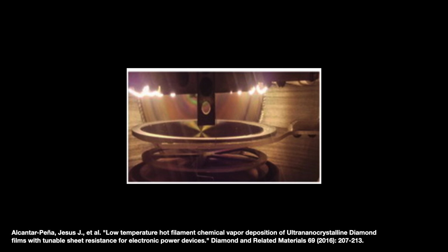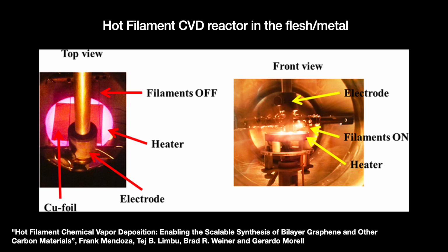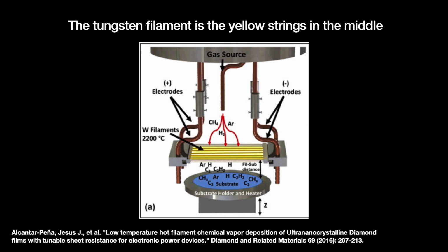To speed things up, scientists introduced nitrogen to the process, but as I mentioned earlier, nitrogen atoms make diamonds come out yellow. Not that there's anything wrong with that. Yellow diamonds deserve the same rights as all other diamonds, but a yellow diamond is not as useful for electronics applications, which was what the team at the time was going for. Lastly, and most seriously, there were concerns about the filament. Over time, it might be affected by carbon corrosion and heat, and it might start to warp and bend, affecting the deposition rate. Worse yet, the filament material, tungsten, can contaminate the growing diamonds.